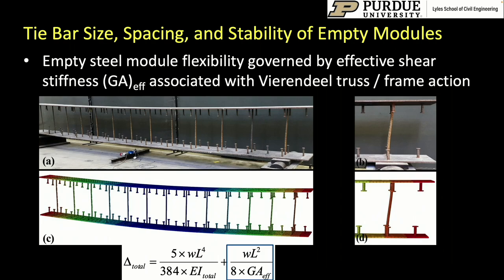What we found from our studies was that the empty steel module flexibility is governed by the effective shear stiffness, which is associated with Vierendeel truss or frame action associated with the tie bars. Looking at the experimental data and the numerical models, we were able to develop equations for calculating the stiffness of the empty steel module. And what we found was that its shear stiffness was the key. In fact, the shear stiffness was far more important than the flexural stiffness of that empty module.